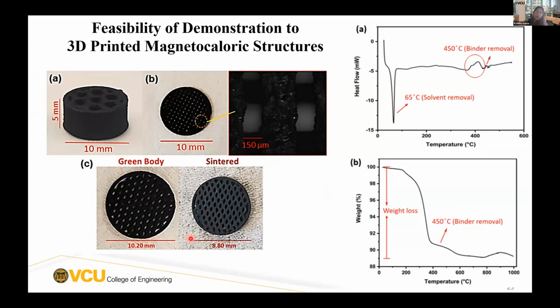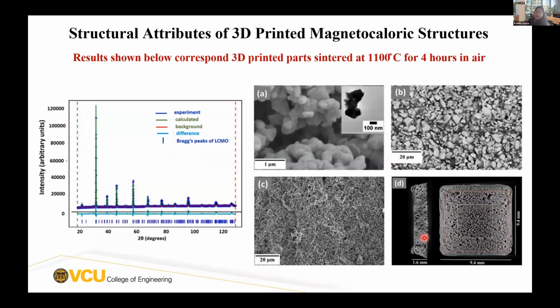Once the parts were made and shrinkage was observed during sintering, the sintering protocol was determined using DSC, differential scanning calorimetry, and we found that 450 degrees is optimal to remove the binder. All samples were sintered first to 450 degrees Celsius to remove the binder, then to higher temperatures to achieve densification.